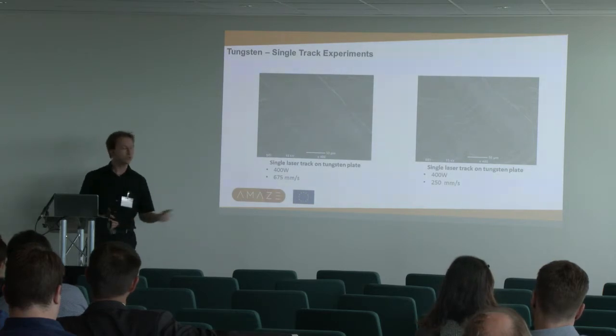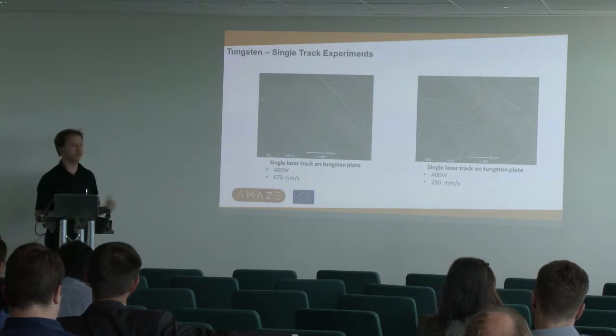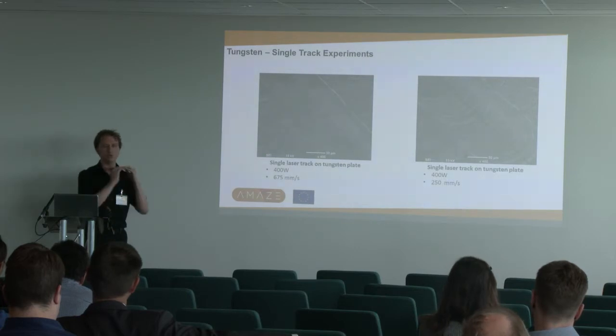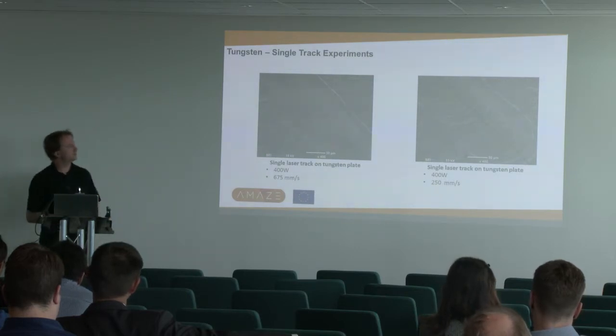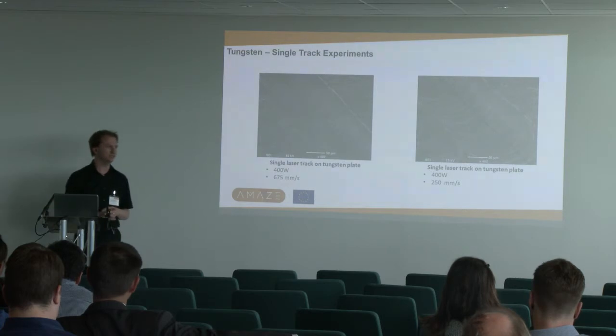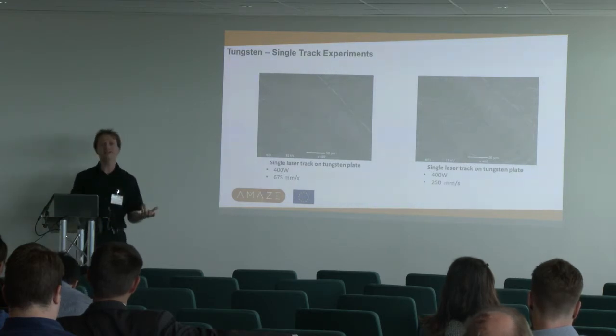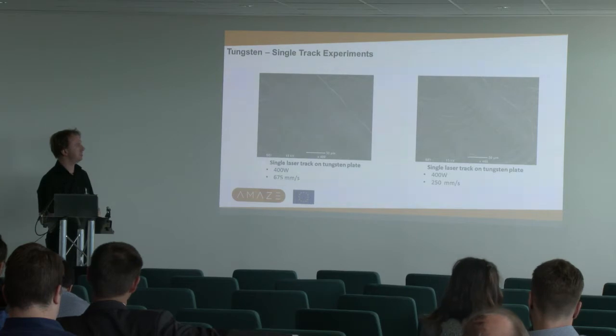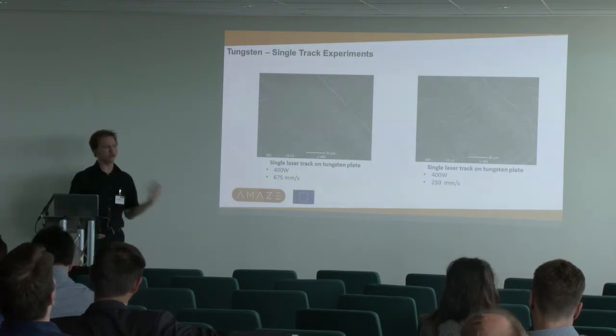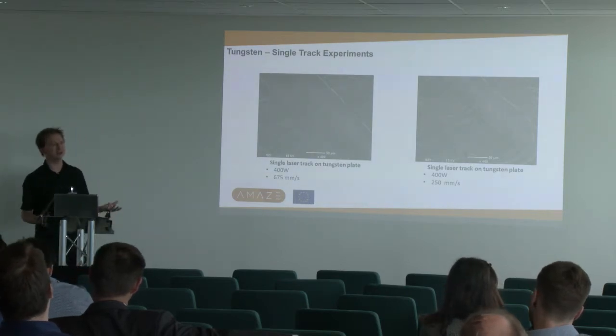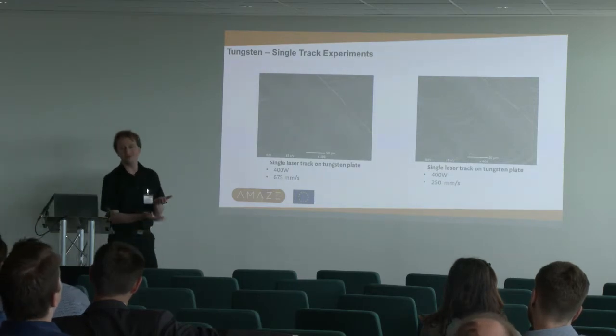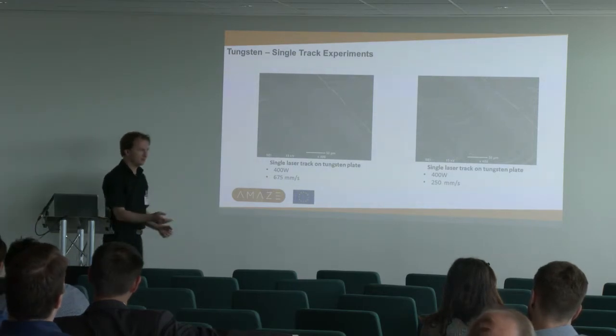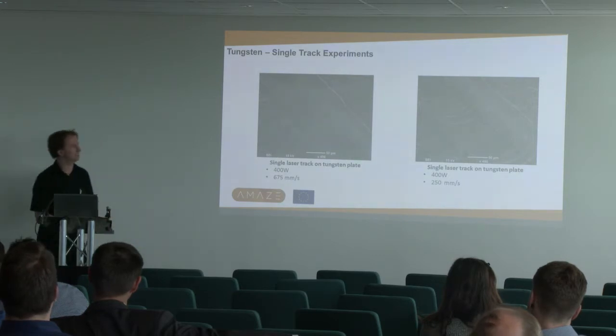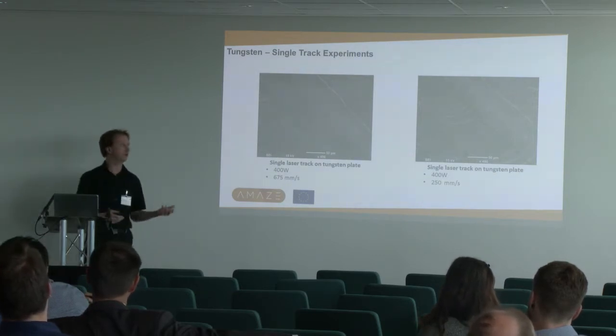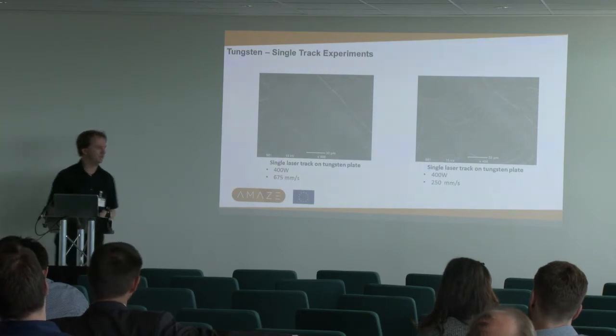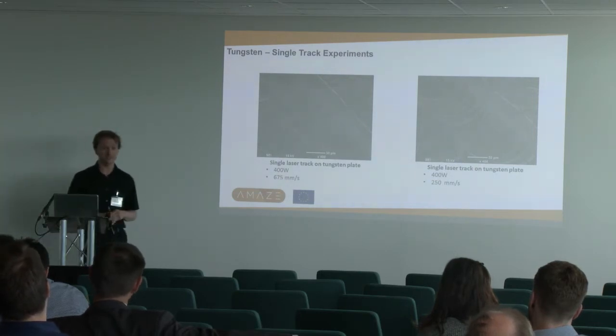Centerline cracking is of course quite common in welding literature, where you see a big centerline grain boundary forming a weakness down the center of the weld. With tungsten especially, given how messy the additively manufactured part is, it's worth going back to basics. Whenever we do metallography on additive parts, it's always a little bit like archaeology. You've got hundreds, maybe thousands of layers all on top of each other, with possibly hundreds of thousands of laser scan tracks and defects building up on each one. So it's very difficult to work out what's going on. A little bit of fundamental work is certainly justified in this case.